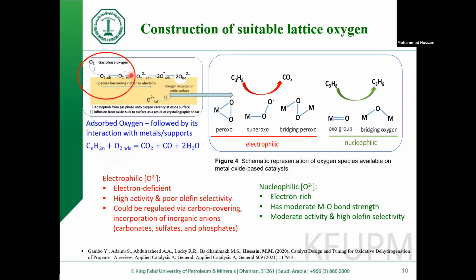Now, the oxygen that escapes this adsorption phase may interact with the active site and become lattice oxygen, and there are two types of lattice oxygen, electrophilic and nucleophilic. Electrophilic oxygen is electron deficient, and these are highly active. However, these are poor for olefin selectivity, so they are not desirable. However, in terms of conversion, these lattice oxygens are good. So one can consider this in a very controlled way to secure high conversion and get appreciable selectivity. The third type is nucleophilic lattice oxygen, which is electron rich and has moderate metal-oxygen bond strength. It gives moderate activity, however, high olefin selectivity.